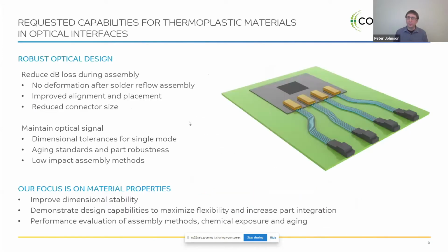And so the core of it, I think, comes down to a robust optical design. This comes into two different factors. One is the reduction of the signal loss during assembly. This is where, as you move to a co-packaged optic and you start to need solder reflow assembly, there's no deformation as you go through that lead-free solder reflow temperature of 260 degrees C. It could also be something where we're trying to improve the alignment or placement of the fiber optics themselves to make sure that they align properly with your laser source or your photodiode. And then, of course, there's always something on the reduced connector size, because as you start to concentrate more and more fibers, you also need to start concentrating that in the connector as well.